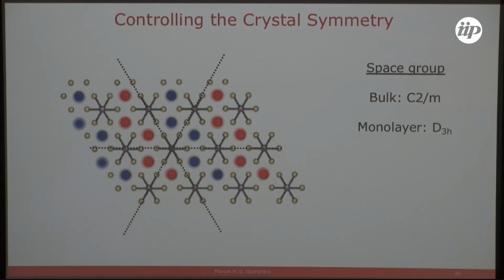And now if you go below the Néel transition temperature, you induce magnetic ordering in this material, and nickel thiophosphate has a nice zigzag order. So you break 2 of these mirror planes and you're left with just 1, exactly like what we had for tungsten ditelluride. Right? So it's pretty nice. And then we reduce the symmetry to Pm or Cs.